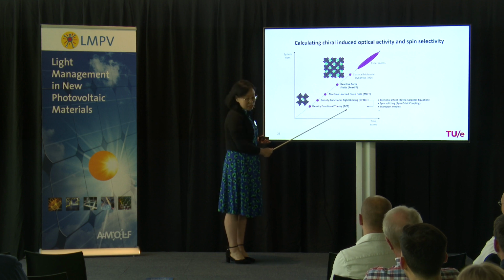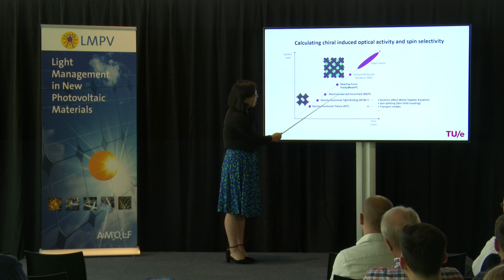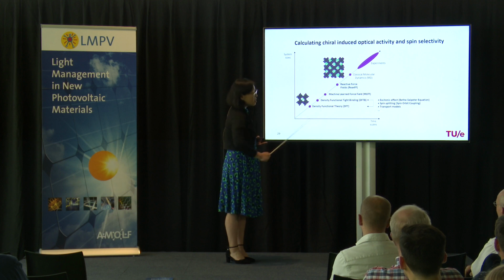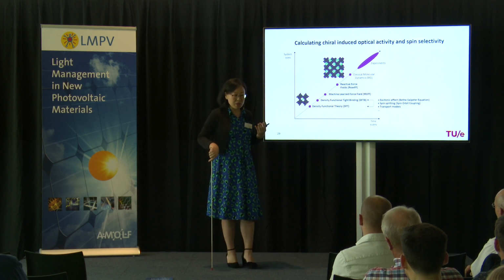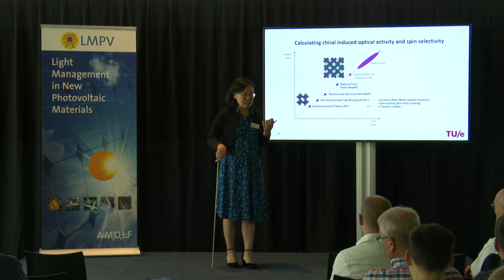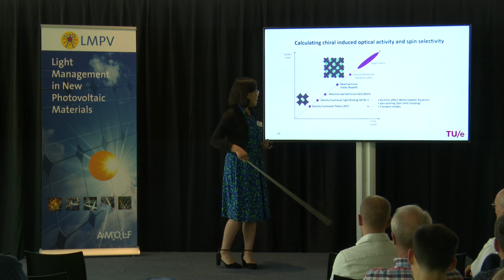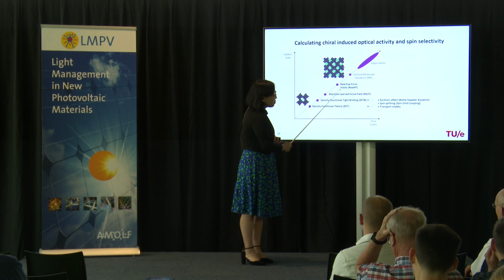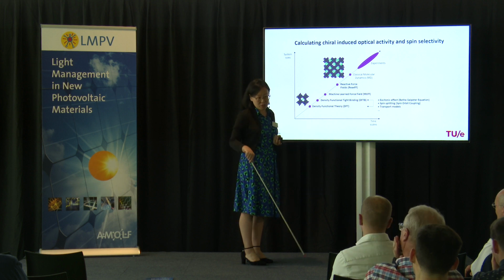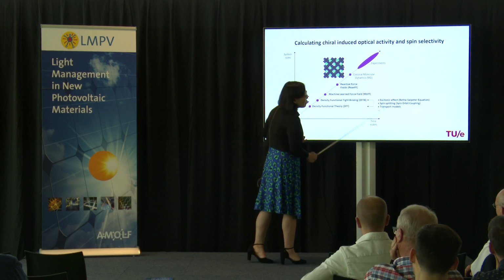We actually use DFT as a starting point to get the wave function. We build a tight-binding model to incorporate the chemistry and the electronic properties there. In this model, we can simulate large structures. We can simulate many different structures, and we plug in all the